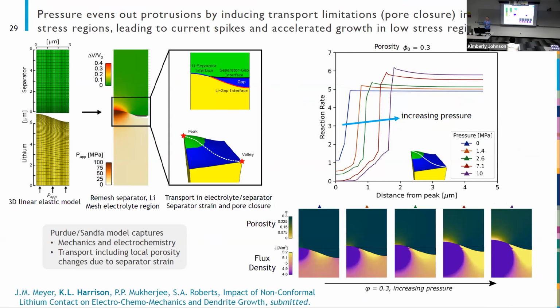And we looked at a slab of lithium with a rough surface and a separator. We move those two surfaces into contact such that there's a pressure applied and do a linear elastic model, remesh that electrolyte region, and solve for the pressure. And then we also include things like strain in the separator and the possibility of pore closure if that strain gets too high, and solve for transport in the electrolyte region in the gap space and in the separator. And so by doing that, we can actually understand how that pore closure changes the transport of lithium ions and the ability to actually form lithium at the surface.